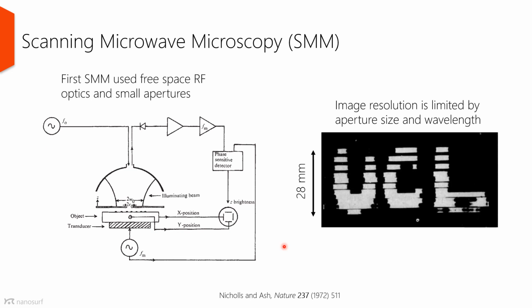So the first idea of scanning microwave was realized almost 40 years ago, but at that time it was not really a scanning probe method. It used free space microwave optics instead of cantilevers to deliver the microwave to the sample and measure their reflection. But already then, the signal that they measured was the reflection coefficient of these waves. And as you may expect from this free space optics, the lateral resolution of such a method was severely limited by the wavelength. But these researchers have managed to push it to the sub-wavelength resolution by introducing this small aperture through which the waves were released onto the sample.